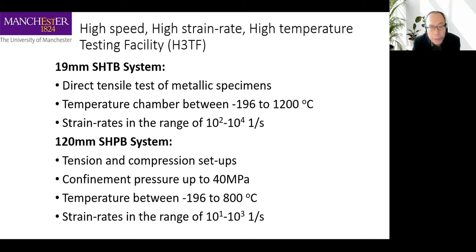This is for the high speed, high strain rate, and high temperature testing facilities. The purpose of this is to get material properties out of these different environmental parameters, so it is normally related to extreme loading conditions. So we have 2 split Hopkinson bar systems, which are used mainly for high strain rate combined with temperature and pressure. One is the 19 millimeter one, mainly for metals. So we can test samples from nearly minus 200 degrees to 1,200 degrees Celsius, and the strain rate between 10 to the power 2 and 10 to the power 4. So this is roughly sufficient for the normal impact and blast loading scenarios.